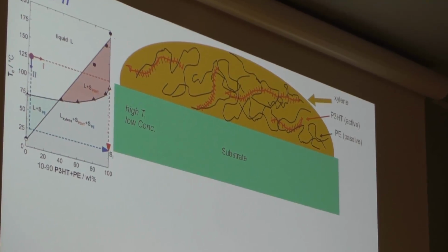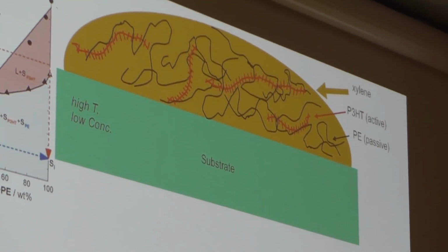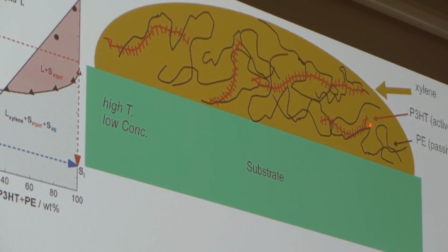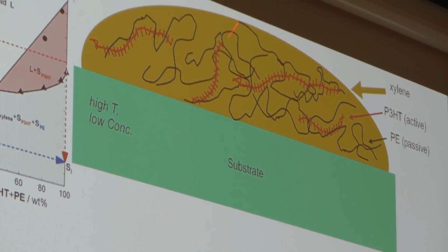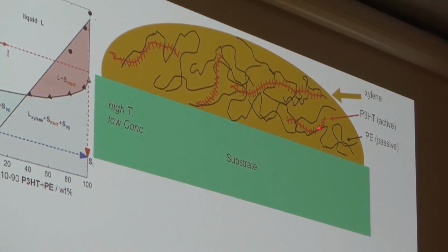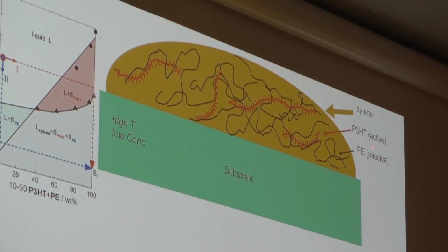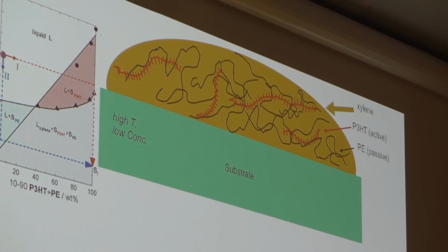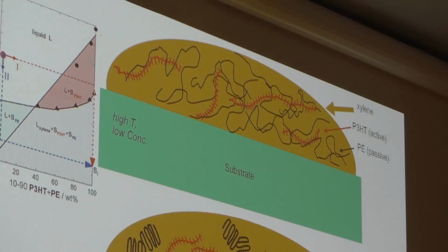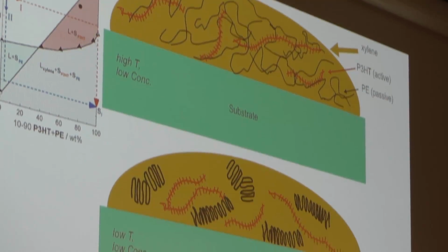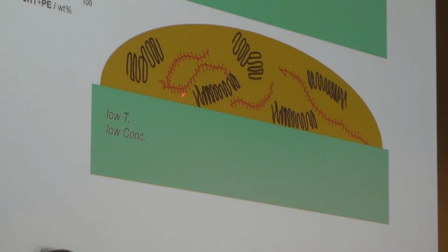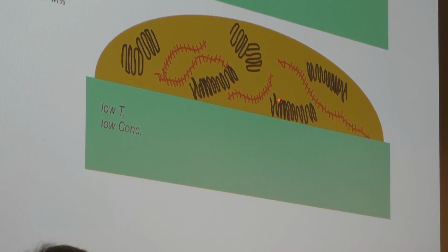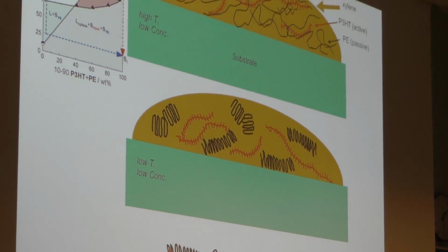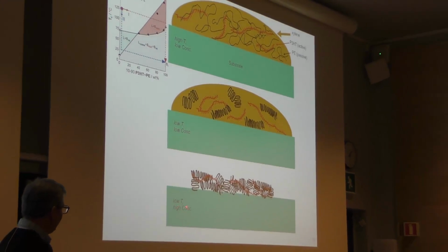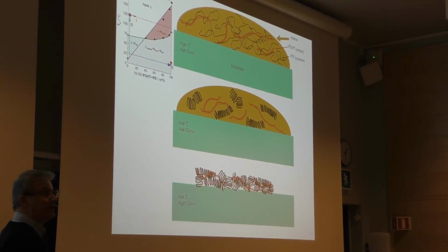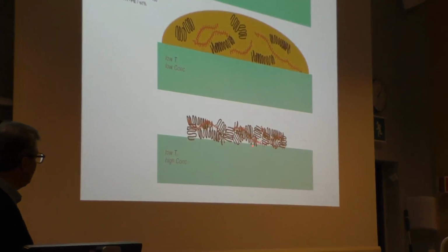So let's look first at route number 2, which is that we first cool down. So you can imagine that these reddish things here are a schematic illustration of the polyhexyl thiophene polymer strands. The black ones are the polyethylene, which is again a passive material, and it's in a drop of xylene. So we first reduce the temperature, and you can see that the material, the polyethylene, crystallizes here. And then when we finally let the solvent evaporate, we arrive at something that schematically looks like this.